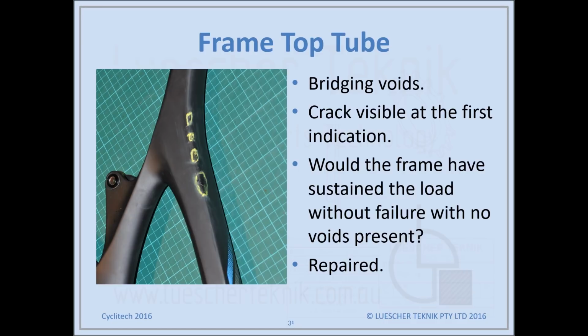In this case, you can see marked in yellow the series of bridging voids, and then there was a crack. The crack indication was also here, which was what the customer originally brought it in for. When we scanned it, we found all these other areas of bridging voids, so it's clear that the crack indication presented itself due to those voids. In this case, we could repair it. We could rebuild that section of the bike, sort of. All through this section on that corner was repaired.